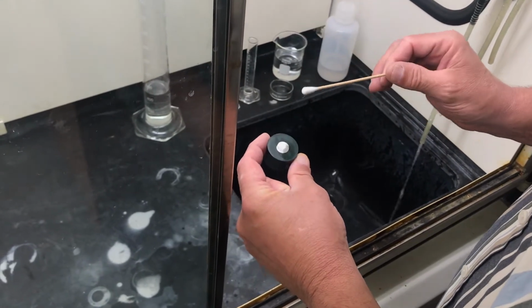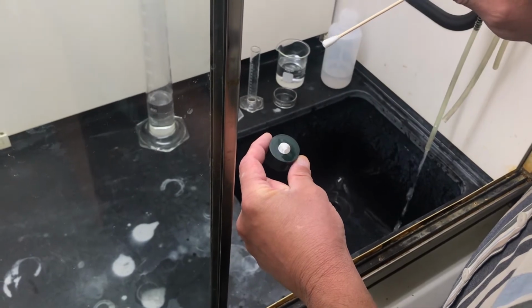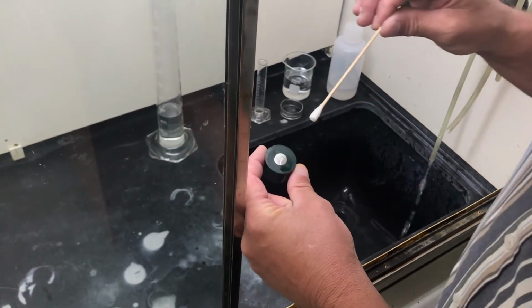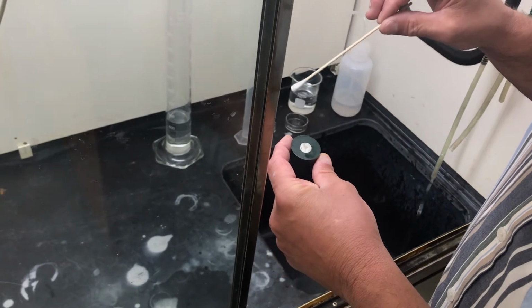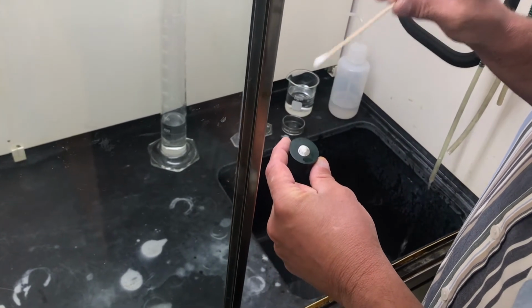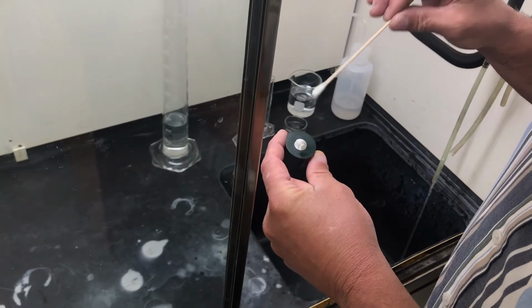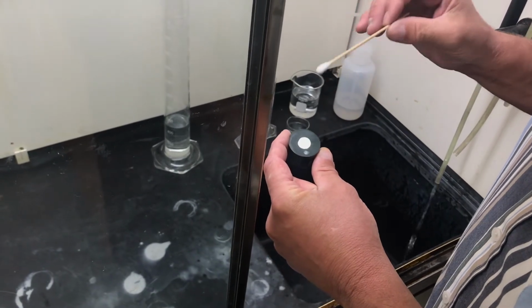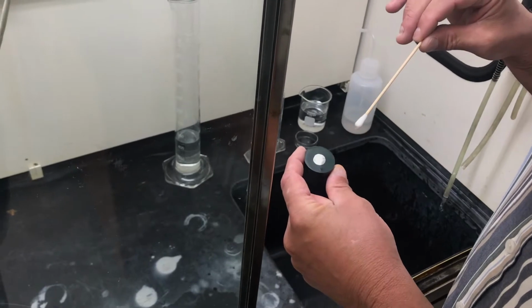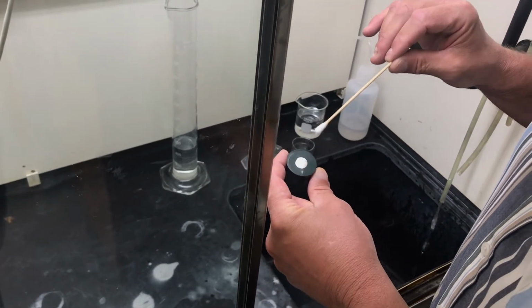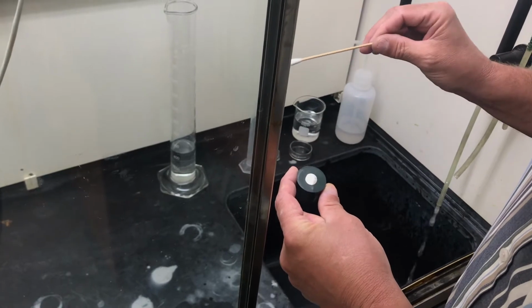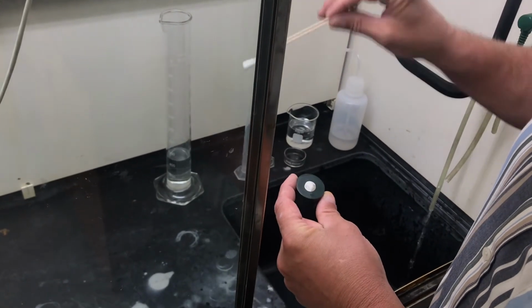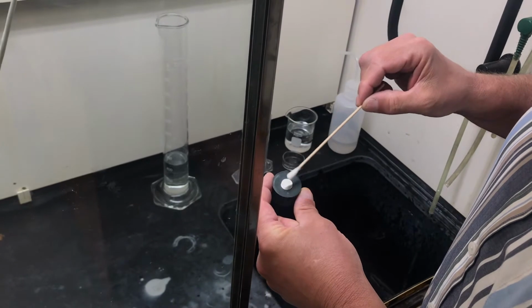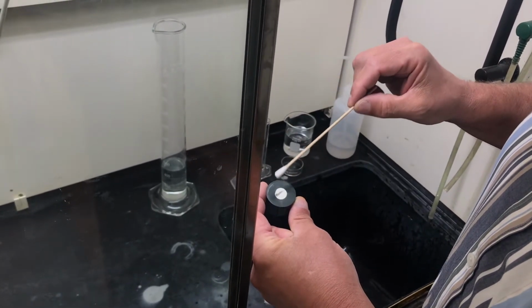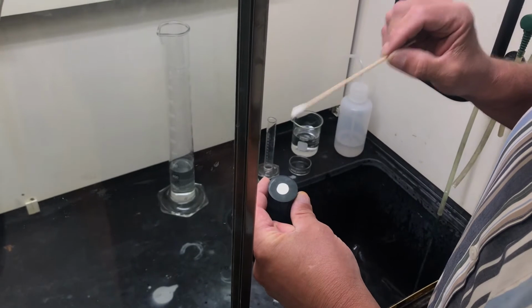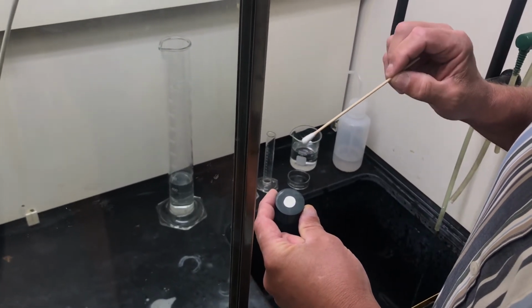The reason we're doing this is that the etchant will preferentially etch the microstructure, grain boundaries, and other features of the microstructure so that you can see them under a microscope. Without the etchant, all you would see is shiny metal. But what you want to see in this lab is microstructure. I'll show you how we see the microstructure in just a minute. But just so you understand the purpose of this, the acid is used to preferentially etch the sample to achieve microstructure that you can see under a microscope.